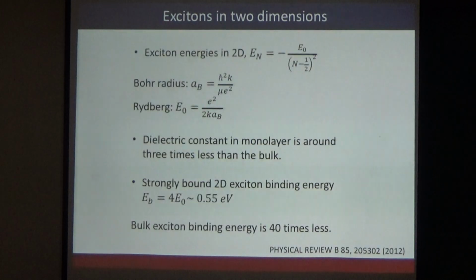So these are called excitons, and since these are confined in 2 dimensions, the interesting thing will happen because the electron and hole are confined in 2 dimensions, their energies will be defined by this factor, just like a hydrogen atom in 2 dimensions. You notice a factor of n minus 1/2 whole square. So if it was a 3-dimensional case, there would be no half factor here.